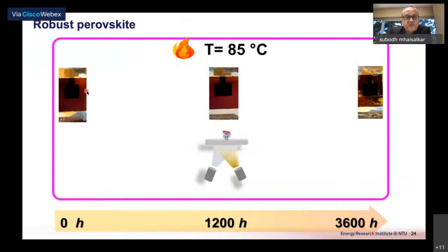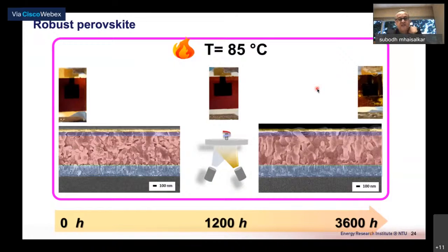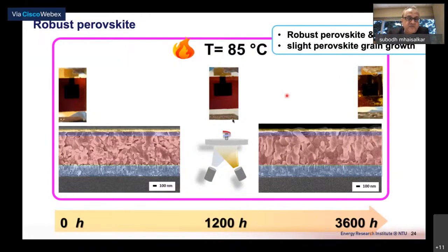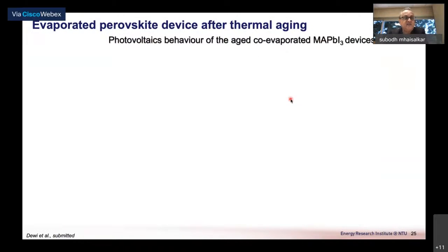So just to zoom in a little bit on the 85-degree performance, what we see is at about 1200 hours, there's practically no change in the perovskite itself. But as the perovskite is stored at 85C for 3000-plus hours, you begin to see degradation at the edges. And it's really the edge-based issues that we need to tackle. As you can also see in these images, there really is not a significant change in the perovskite material itself, but most of the changes are happening at the edges of these devices.